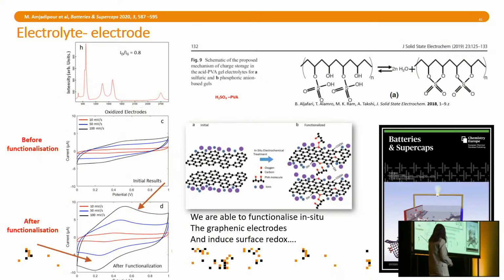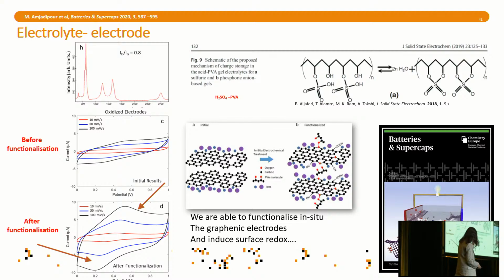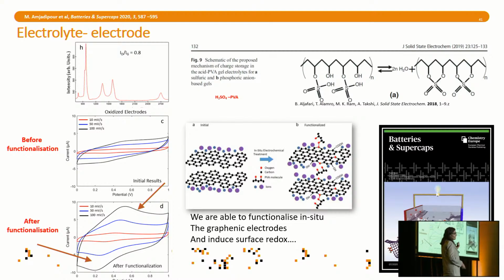Then we also found a way to trick it. Remember that we had this 100 nanometer small, and here definitely much smaller, grain size. It turns out that that grain size can be easily functionalized, but here, just in presence of water. So what happens is that you attach, for example, OH groups in the presence of water, and that makes the system very hydrophilic. And at that point, you can even improve the intercalation further than with a system that is more hydrophobic, like plain graphene.